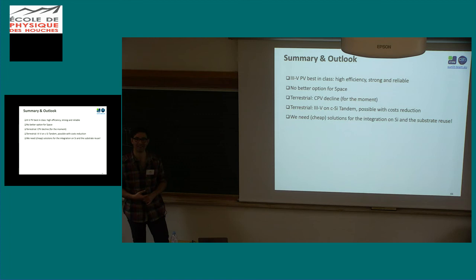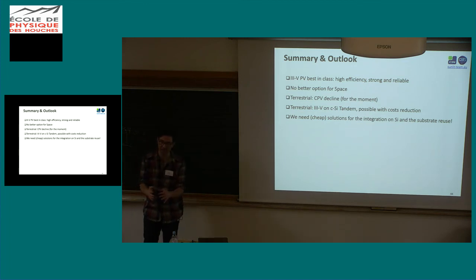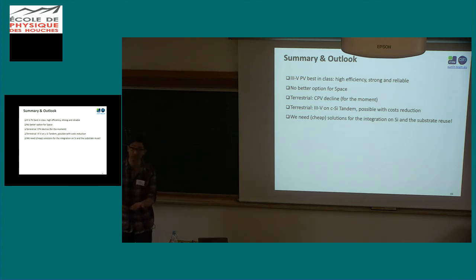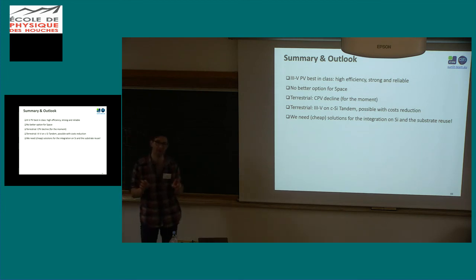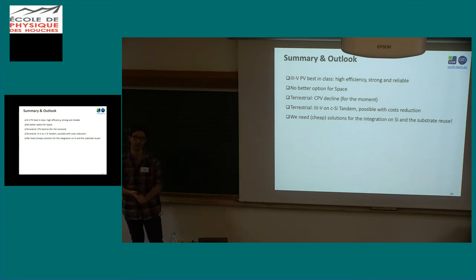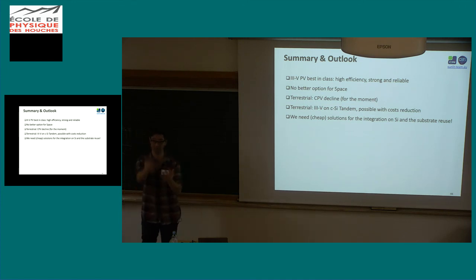Yes? That graphene you talked about, is it lowering the surface energy also? Screening. There's another nice paper where they measure the surface energy of the substrate using contact angle measurement, trivially, and they show that whenever they put the graphene, they still have some memory of the real surface energy of the substrate, because the graphene only partially screens this information, which is actually nice. It's more convincing because now there are two experiments done in two completely different fields that show that graphene is somehow transparent to this polar bonding. So it will be a mixture of the surface energy of the graphene plus the surface energy of the substrate, to answer your question.